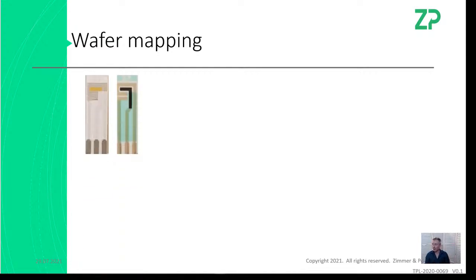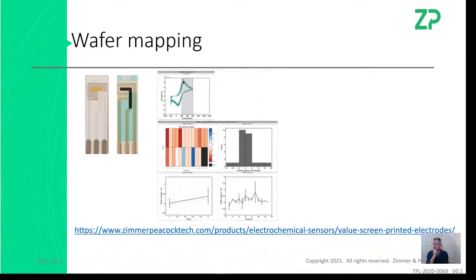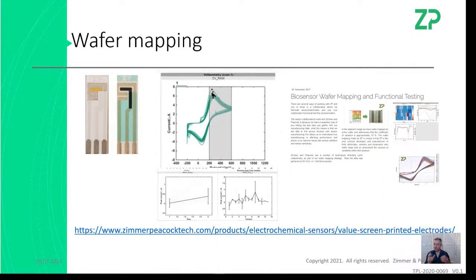It's called wafer mapping. Before we ship any electrodes to anyone, we make sure that we test them all. So we've tested them by ferricyanide ourselves using cyclovoltammetry, and we make sure that all the electrodes in the batch are actually good. So we've got about 50 electrodes in this data set here. So we've done at least 50 tests. We often do 50 tests 3 times. We often test 150 electrodes from a batch before we'll actually bring them into our stock and say that they're good.